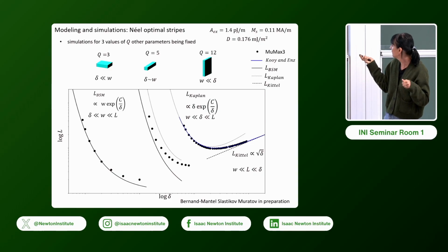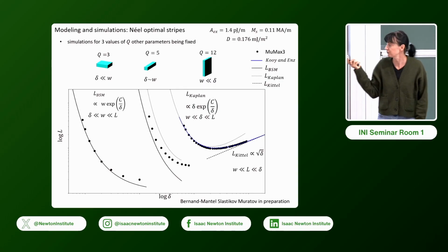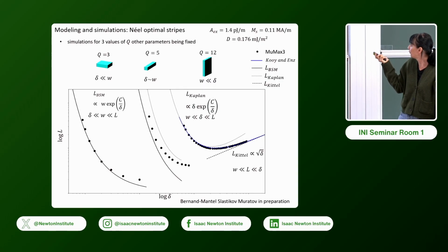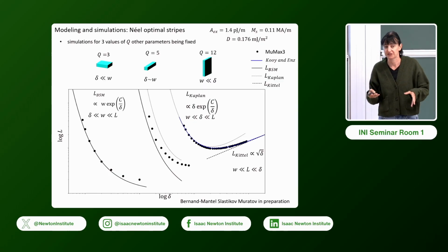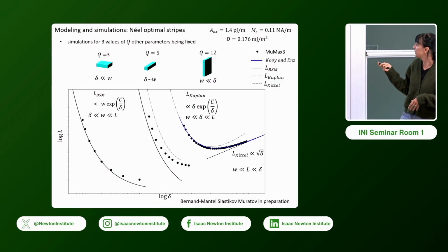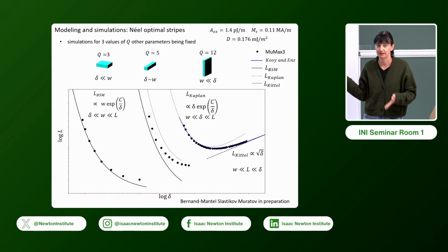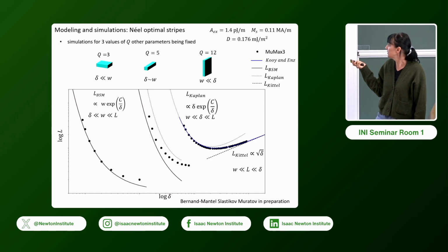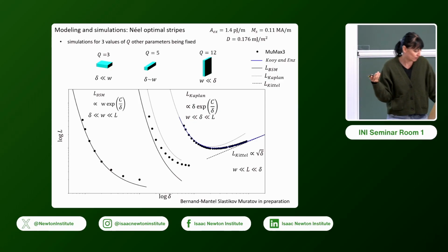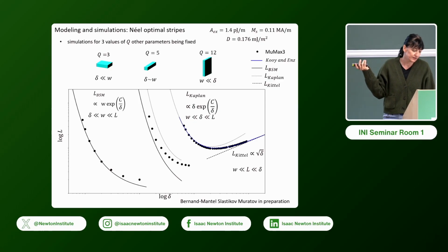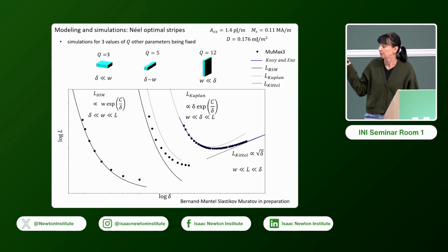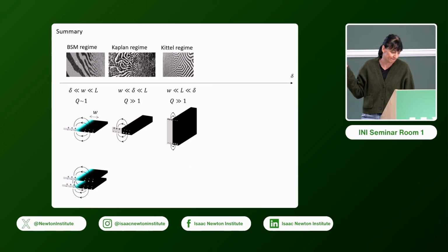And in between, here you need to numerically resolve this stray field energy. Also, if somehow your wall turns out to have a shape which is in between, you actually cannot calculate exactly its stray field energy. So here you see that, okay, these formulas are giving a rough idea about the width, but you have to do numerical experiments to have the exact width.